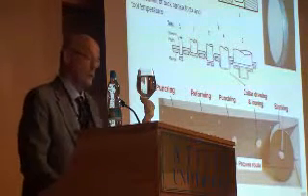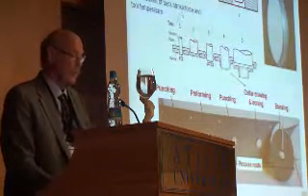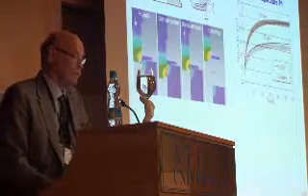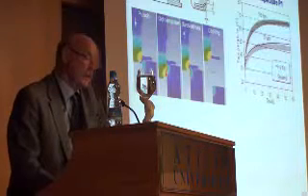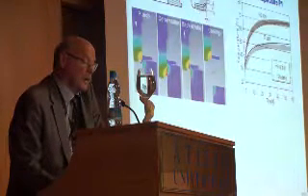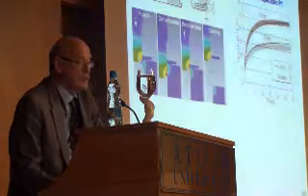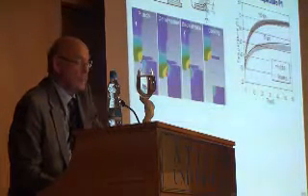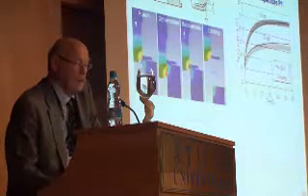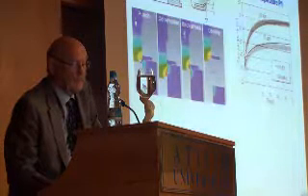We did tests of different lubricants, different reduction speeds, and different workpiece materials, and we measured the backstroke force and the tool temperature in this critical operation. The temperature was measured by mounting thermocouples close to the contact interface from behind, 1 millimeter from the surface, in the punch as well as the die. And you see the development of the punch temperature.